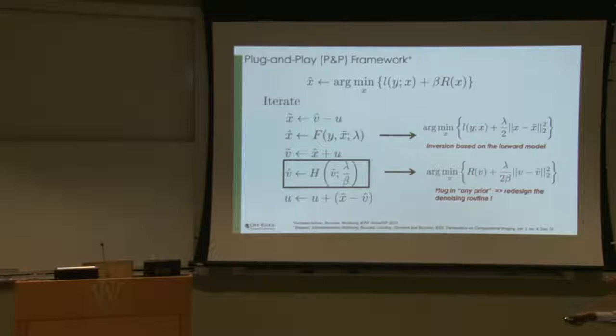The first step often involves an inversion. So you go from measurements to reconstruction, and there's more to it because you kind of regularize the answer. And the second step, you do a denoising, and then you update some variables. So this was inspired by the ADMM, but at the end of it, what we've observed is replacing the second term, which is actually just an image denoising, by any empirical denoiser, still results in convergence in some sense to a fixed point. So this technique is in some way a very different way of thinking compared to just solving an optimization, especially when you start plugging in different denoisers.